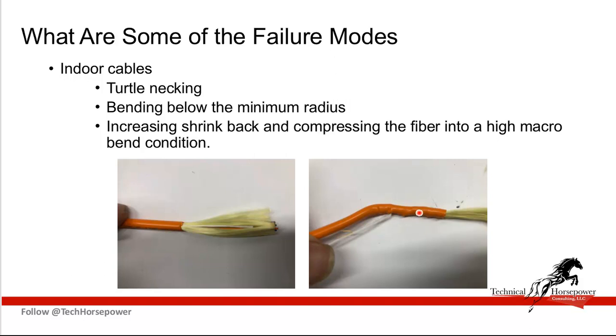And you can see how the jacket, because it's not bonded to these strength members, actually pushes back. And this area right here, where it's crinkled up, is also pulling back the optical fiber, the buffered optical fiber, and causing it to macro bend through this area. And while you can pull it back out afterwards, you may, depending on the hardness of the buffer and the particular design of the buffer, cause permanent attenuation increase or a sensitivity to increase in the future as the cable ages.